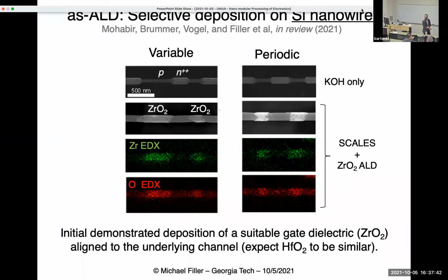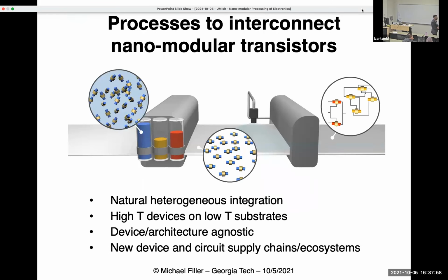Is the zirconia perfect on the nanowire? Certainly not. It needs to have a better morphology. It needs to have cleaner, more abrupt edges. But this is a first demonstration that on a nanowire with a bottom-up patterning process, you can put down a dielectric where you aimed to put it down. And that's the state of the art in terms of wire growth and device synthesis. And I hope to come back soon and show you that these actually work.